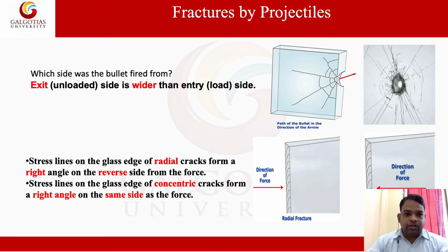For example, the side to which the break came. In a radial crack, the rib mark will be nearly perpendicular to the unloaded side and nearly parallel to the loaded side. The thing will exactly reverse for concentric cracks, which grow in the opposite way.